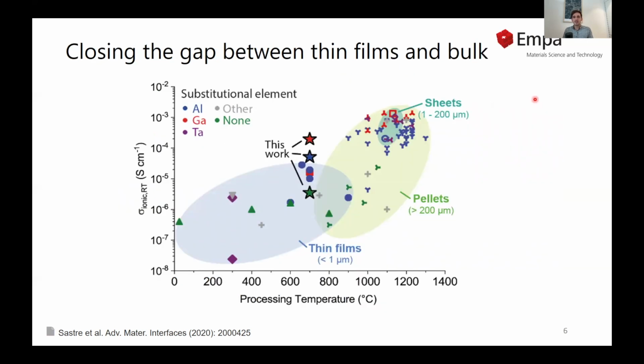With this process, and by adding substitutional elements like gallium and aluminum, we could push up the ionic conductivity values for LLZO thin films while retaining a low processing temperature of only 700 degrees. Especially with gallium substituted LLZO, we were able to achieve an ionic conductivity of 2 × 10⁻⁴ siemens per centimeter, which is equivalent to what has been reported for standard LLZO pellets.